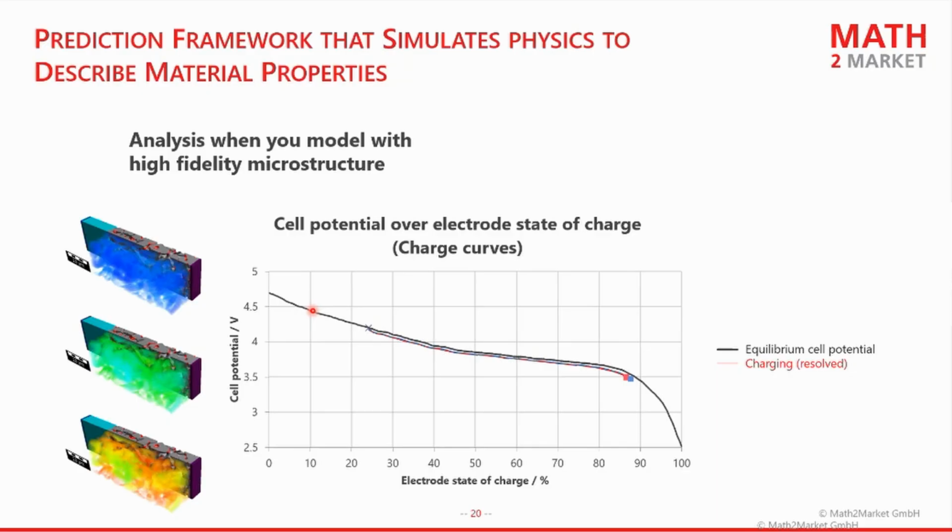She'll take the half cell she just created and start by calculating the equilibrium potential curve, which you see here in dark. This quick 60-second routine will establish a reasonable voltage interval as our constraints for the charging. Then she'll proceed to set a charge rate and run a lithiation simulation of charging the cathode.